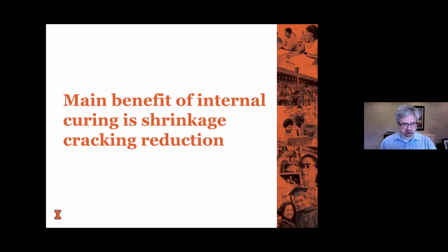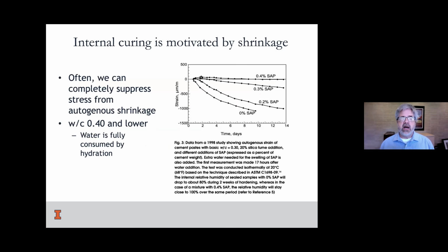So the main benefit that we're aiming for here is shrinkage cracking reduction. And these are some charts of the strains that we get from autogenous shrinkage. And you see when we have 0 SAP, we have, in this case, 1,000 microstrains of drying shrinkage and autogenous shrinkage. These are sealed samples. But as we use SAP, we can offset that, because the system works to avoid desiccating the microstructure.